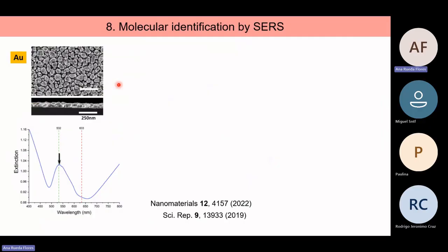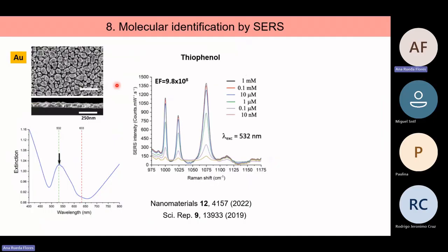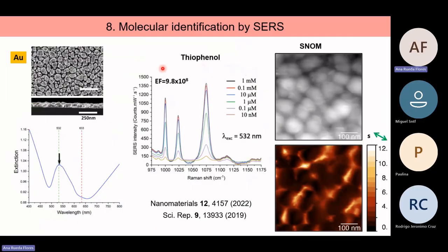In this case, we would like to detect thiophenol, which is a molecule used in the pharmaceutical industry. You can see the Raman spectrum of thiophenol. The peaks correspond to thiophenol, and we are decreasing the concentration. We started with 1 millimolar, and we decreased down to 10 nanomolar, and we were still able to detect the peaks of the thiophenol. In fact, the enhancement factor, thanks to these gold nanocolumns, is almost 9 orders of magnitude. And the reason for this enhancement is a plasmonic effect.